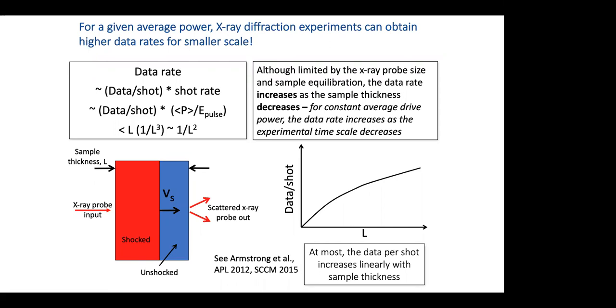So if you go from an experiment that requires a 10 nanosecond drive to an experiment that requires, say, a 1 nanosecond drive, you'll save a factor of 1,000 in energy, which is very nice for a couple of reasons. One, because the lasers can be much less burdensome to use. But then also something that doesn't come up much is that there is a change in rep rate for lasers between about the 100 joule to kilojoule level to the sub 100 joule levels. So if you're operating with a hundreds of joule laser, then your typical rep rates are going to require something like, maybe an hour of cool down between shots.